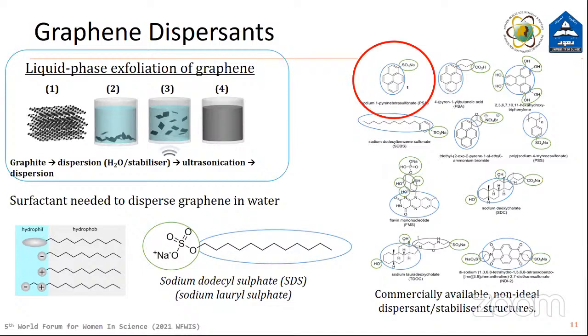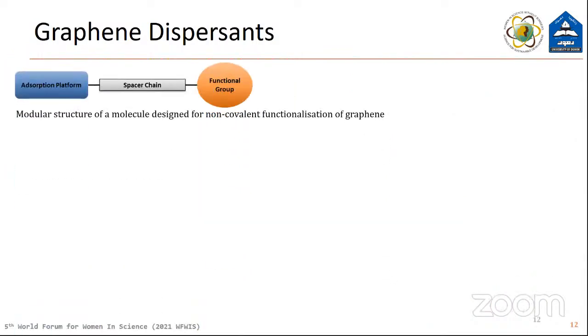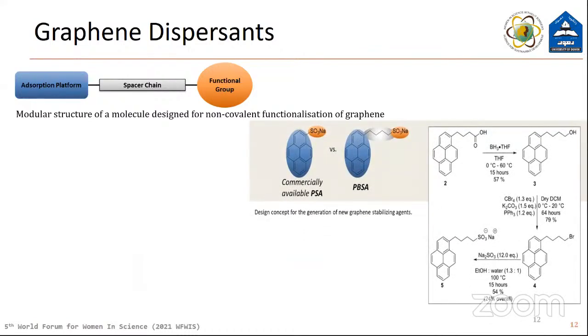Among all these stabilizers, pyrene 1-sulfonate, PSA, is one of the most frequently reported small molecule stabilizers in the literature. So building on this, we built a modular structure of a molecule designed for non-covalent functionalization of graphene. In a preliminary study, the stabilizing ability of commercially available PSA and pyrene butyl sulfonic acid salt, PBSA, was compared. PBSA was synthesized in 3 steps as shown in this scheme.